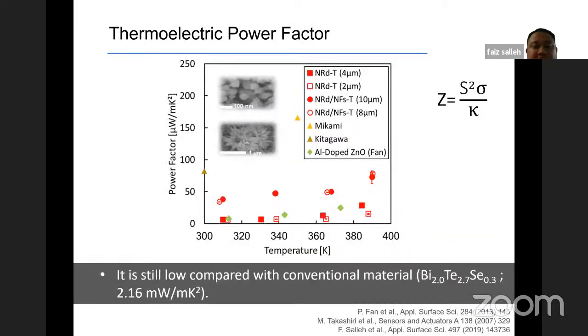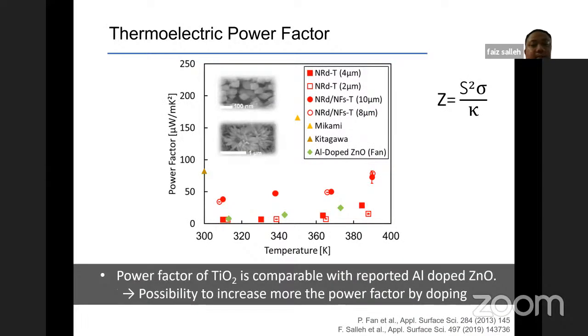And then, since I already mentioned that there is a possible increase in the power factor by doping, and we also know that these thermoelectric parameters strongly depend on the carrier concentration, next we want to clarify the influence of doping on this nanostructured TiO2 thin film, especially on the thermoelectric power factor and also the nanostructure itself. Why? Because if we cannot preserve the nanostructure, we can lose the benefit of reducing the thermal conductivity, because we know that when we introduce nanostructure inside a material, we can increase the phonon scattering, boundary scattering, and so on to reduce the thermal conductivity.